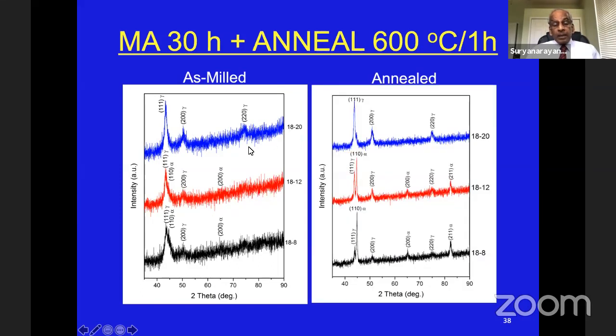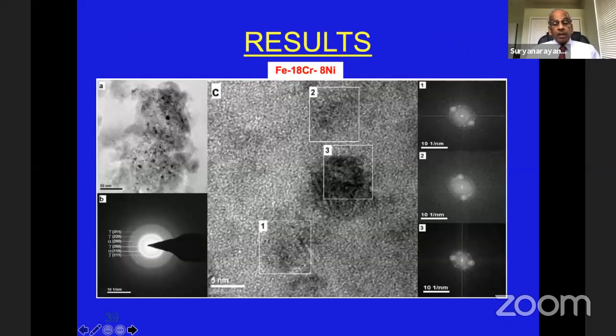Now, if we anneal this, obviously the patterns are going to be much more clear. And here again, you will see, even after annealing, you still have some ferrite in both 12 and 8% nickel, but 20% nickel, obviously, because there is no ferrite here, here also you do not see any ferrite present at all. So what we did was look at the electron microscopy results.